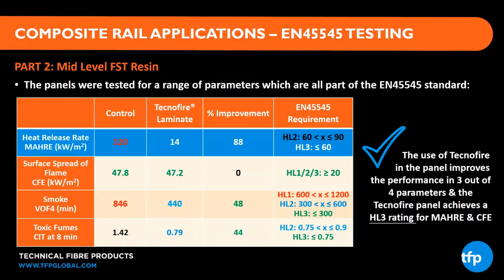That's one of the lowest heat release rates I've seen with a styrenated vacuum-infused composite panel. And there's obviously some interesting synergy occurring between the intumescent Technofire mode of action and the fire retardancy that's built into the base resin. And again, if you look at the requirements, HL3, the highest hazard level, defines a maximum heat release rate of 60. We're down at 14. So we've significantly improved the way that that composite panel performs in a fire and how much energy it liberates, how it feeds the fire.